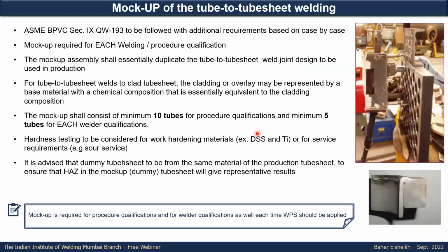One of the main features you have to respect and do in high quality and properly is the understanding of the mock-up of the tube to tube sheet, especially for the welding application. We will see in ASME Boiler and Pressure Vessel Code Section IX, QW-193, the recommendation for the application of the mock-up. Each welding procedure should have a mock-up, and also for each welder qualification you should have a mock-up. For the welder qualification, you should have a mock-up with minimum 5 tubes, and for the mock-up for the procedure qualification, you should have minimum 10 tubes. And the material should match the material which will be used in the production.